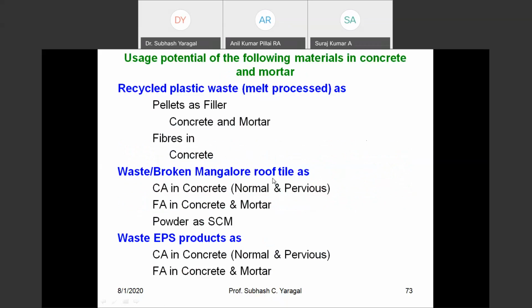Now, apart from using the broken Mangalore tiles as coarse aggregate, as fine aggregate, and as secondary cementitious material, we have also done a lot of work on using recycled plastic waste. I'll show you. We do the melt processing of domestic plastic waste, which is thrown away or abused. We use the plastic, prepare pellets out of this melt processed plastic, and use it as a filler or a small, maybe 10 to 15% replacement to river sand in concrete and mortar. You can use fibers out of this MPP in concrete. We have also done studies on EPS products. We have used thermocol, the packaging material, as coarse aggregate in concrete, both in normal concrete and in pervious concrete. We also use this material in concrete and mortar.